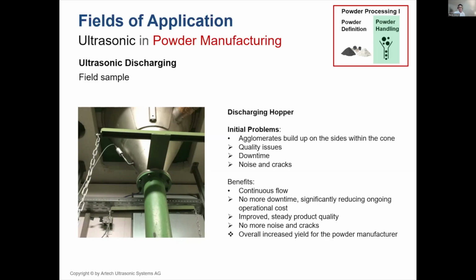Accordingly, the customer, before using ultrasonic, had to clean the inside walls many times, and they used loud mechanical knockers and air, very energy inefficient technology. So with ultrasonic, we were able to ensure continuous flow. There was no more downtime, significantly reducing the ongoing operational costs. We could improve the product quality, no more cracks in the hopper, and overall the end customer was really happy because we could increase the overall yield for them.